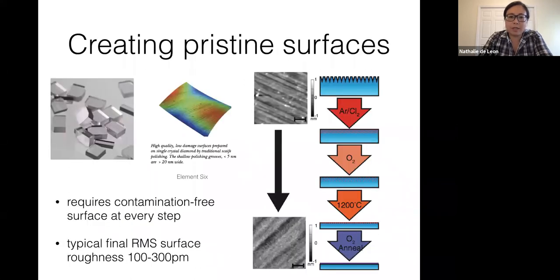So what we discovered is that in order to really control this surface morphology, what we had to do was really avoid any contamination at the surface at every single processing step. And then to deal with the fact that diamond is such a hard material, we had to do iterative processing to basically remove the damage that was done from the previous step, and then iterate through that until we could get to a very smooth surface that we could control.